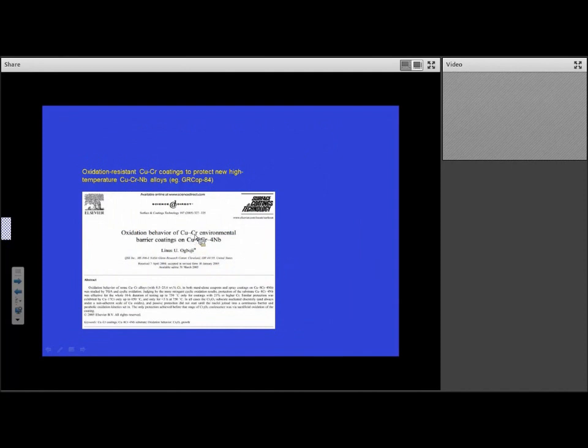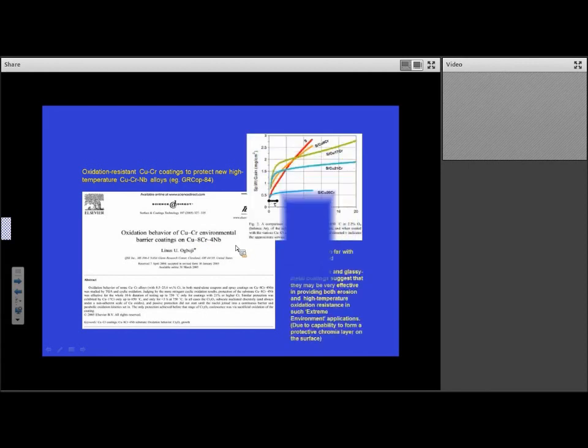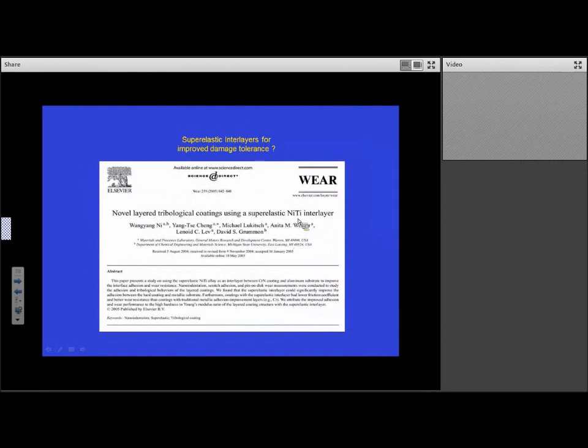Many papers now out there on things like chrome copper films, and this is a situation where this particular coating is offering excellent protection at high temperature, at 650 degrees C, in terms of weight gain. And the results so far with our chrome copper nitrogen and chrome titanium copper boron nitride have shown that these nanocomposite and glassy metal coatings provide very effective protection in both erosion and high temperature oxidation situations, extreme environment conditions, if you like, sometimes due to the capability to form a protective chromia layer on the surface. And other people are interested in super elastic coatings,